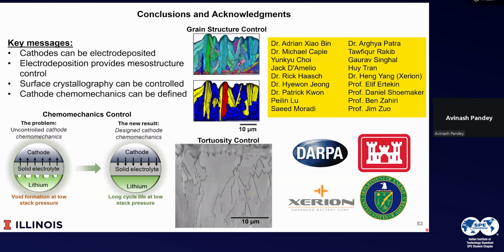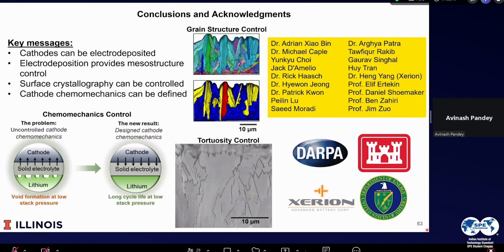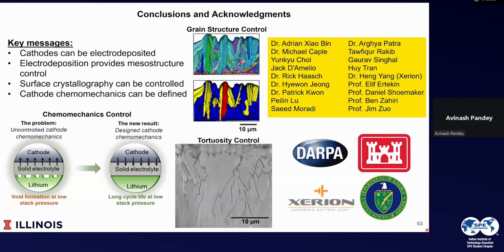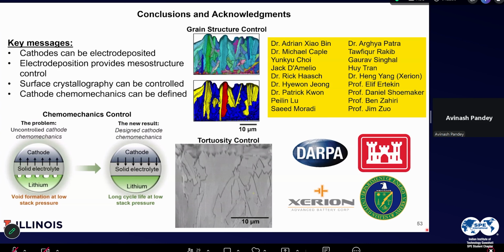So my question was that this electrodeposition technique does provide a very good alternative, since you do not really require a conductive additive or a binder. But how do you ensure a vertical deposition rather than a horizontal one? As you already showed in the results, the horizontal deposition does reduce the capacity, and I believe that the layer stacking on top of one another would eventually cause the capacitance to decrease, right? Restacking of the material would cause the capacitance of the material to decrease. So how do you ensure that vertical deposition?